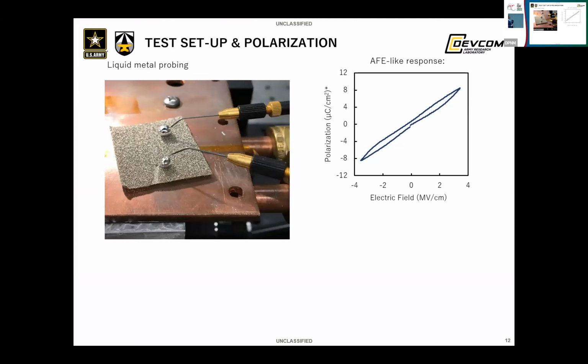Here's what one of the test setups looked like. So instead of having sharp, pointy, scratchy probe tips, I terminated the probes with liquid gallium, and this is one of the test setups where you would have essentially a capacitor in series orientation going on here. And here is the polarization hysteresis that we measured from an annealed foam. It is in the ALD hafnia community considered antiferroelectric-like. I don't have any idea what my area was, but I set the dielectric constant to be correct. And so I added a star there.